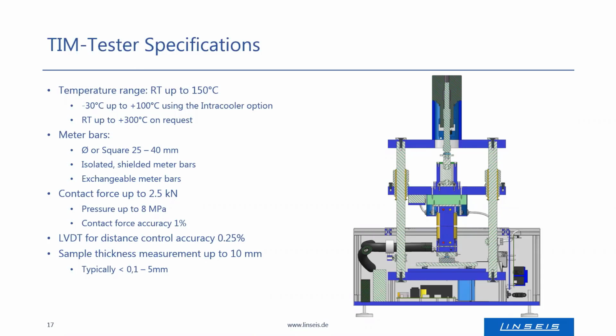The meter bars are either round or square, with the size ranging between 25 and 40 millimeters. They are isolated shielded meter bars, and these can be changed. The contact force, as mentioned, goes up to 2.5 kilonewton, which translates into a contact-dependent pressure of up to 8 megapascal, and the contact force accuracy is 1%.